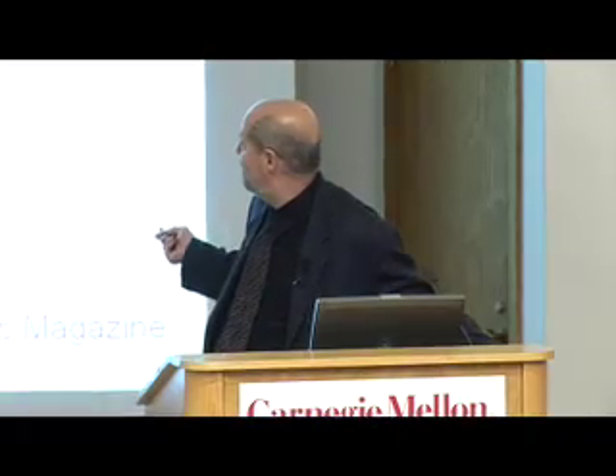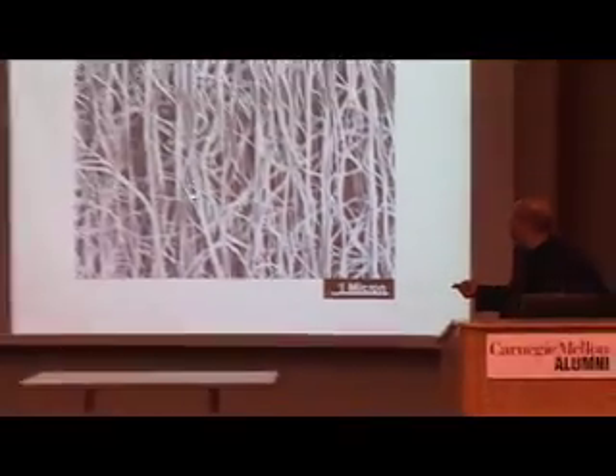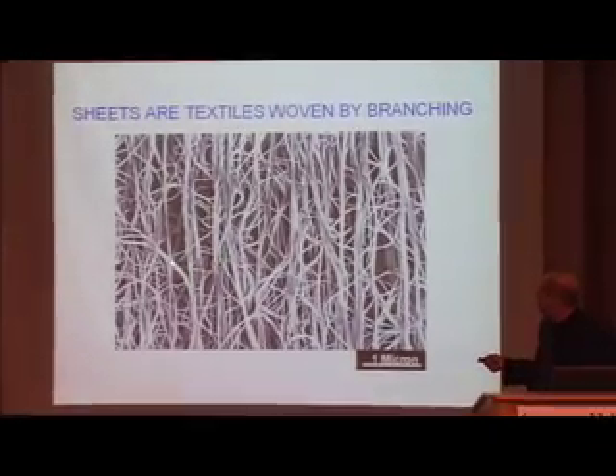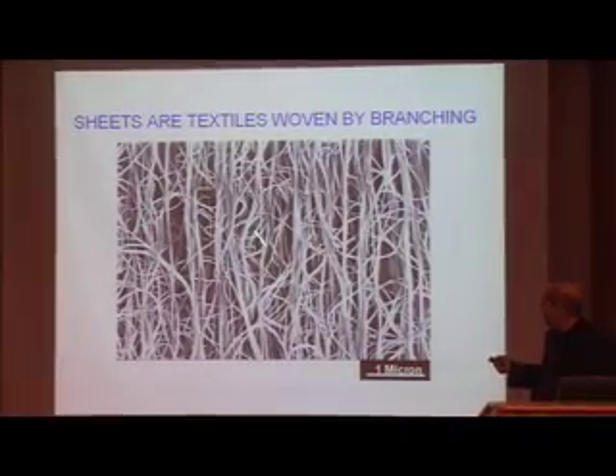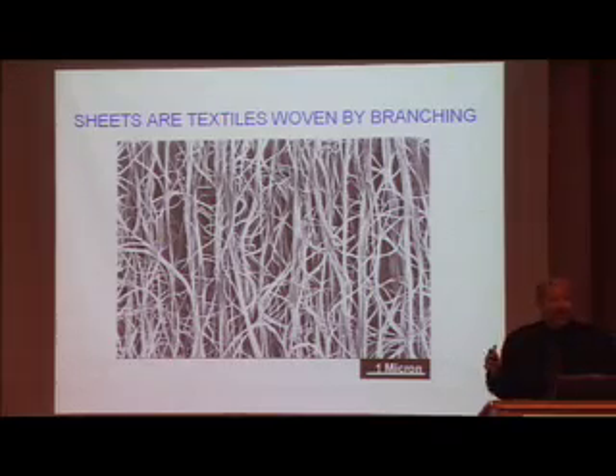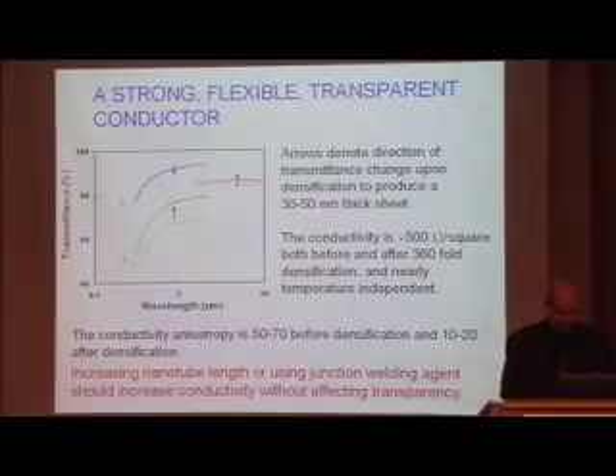Relevant to the issue of bundling, which is a very important question, and also order. Notice that you can see very clear high degree of alignment here. But the degree of alignment is scale dependent. On very high magnification scales, you see a type of self-woven structure where individual nanotube bundles go along and they fork and they combine with forks from other nanotubes in order to make a self-woven structure.